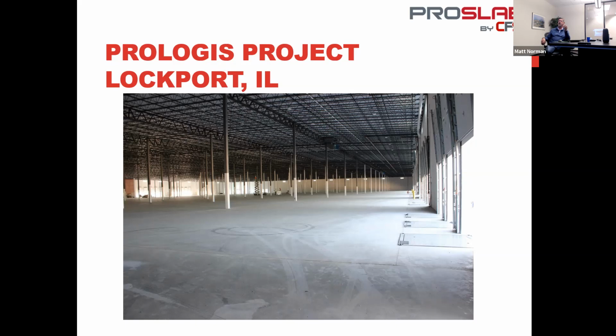You're going to isolate your columns by wrapping them with at least 1 inch of closed cell compressive material. That isolates your column from your slab and allows the slab to move freely. You have to address any reentrant corners, as well as any protrusions through the slab, such as a drain cleanout, something along those lines, electrical cables coming through. All of those have to be isolated.